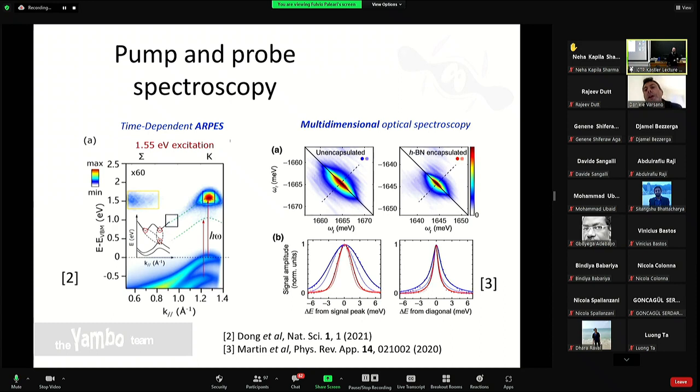So I wonder if everything you said is also valid for core excitons. Is the physics still the same? I think generally yes, but maybe Davide, you can answer this. So I would say that in general for core excitons, the electron-hole binding energy is even more important because the hole is pretty much localized, so it tends to interact a lot. And there are at least two groups who worked on using Bethe-Salpeter to describe core excitons, and it works pretty nicely.